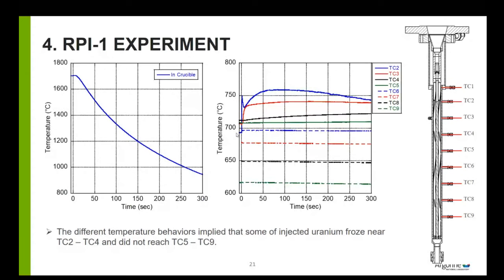So this is the result of the RPI1 experiment. The first graph is the temperature change inside the crucible during the experiment, and the second graph is the temperature measurement inside the test section. TC1 is located at the top of the cladding. TC2 is located near the sacrificial boundary and the top of the alumina filler. Each of the thermocouples is about 2 inches apart. And 0 seconds in the graph means the moment of uranium release inside the pressure vessel.